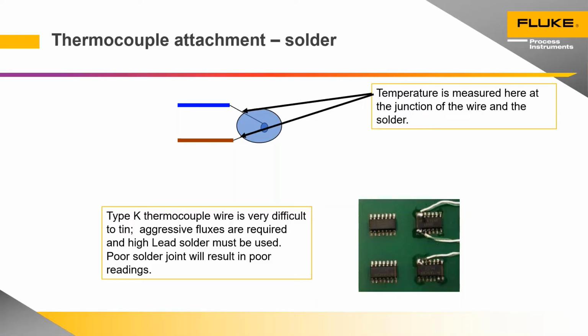You can see some of the issues with soldering in that little picture on the right-hand side of the slide, where the wires haven't wetted at all well in that bottom image. The temperature is actually measured where the two wires touch the metallic solder for the first time. So we're measuring the temperature of the solder bead. The bigger you make it, the more thermal mass it has, the further away from the real temperature that will be. So it's a very good method. You do need an aggressive flux, a high temperature solder, and try to keep that thermocouple bead as small as possible.